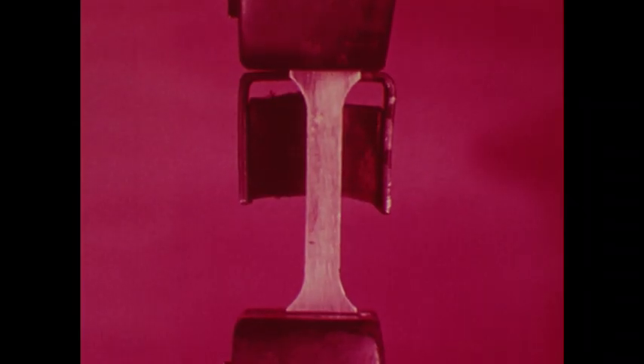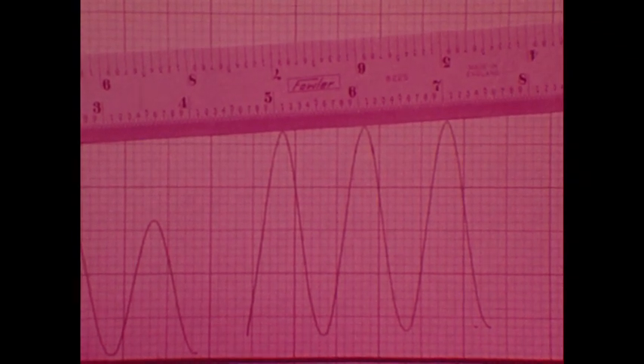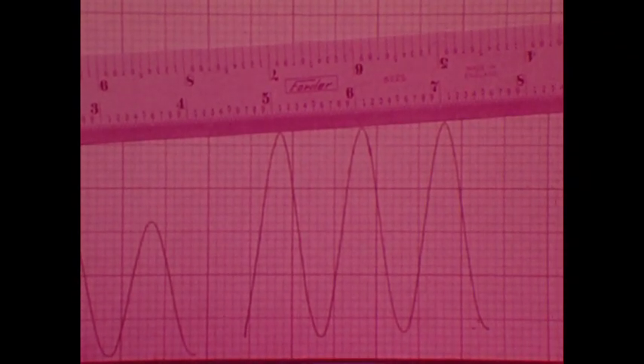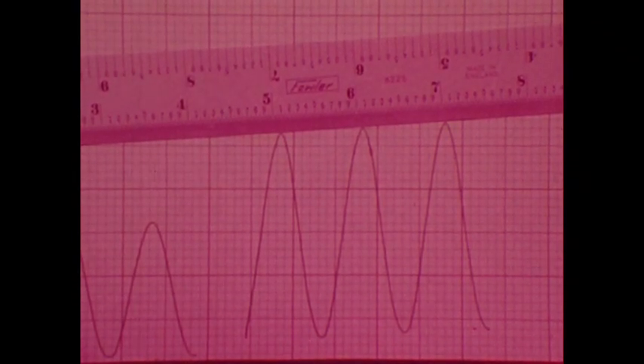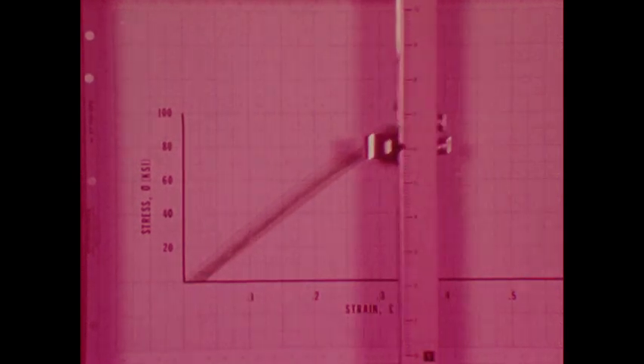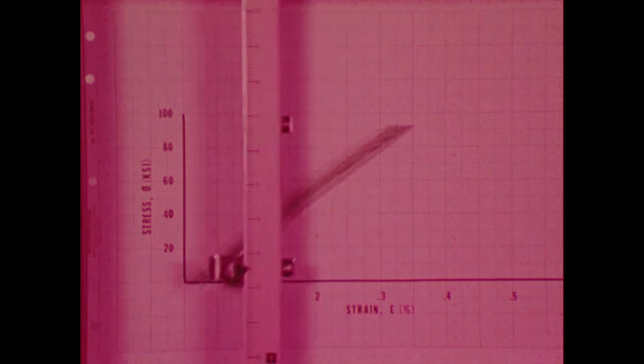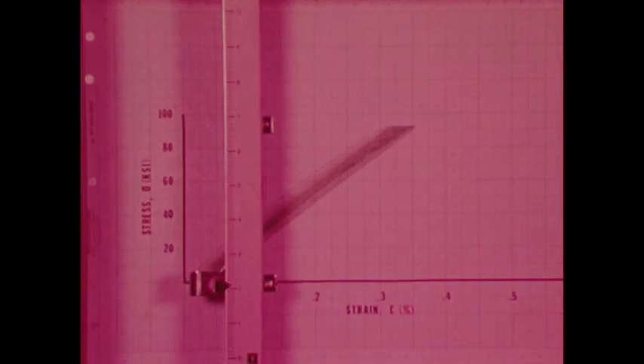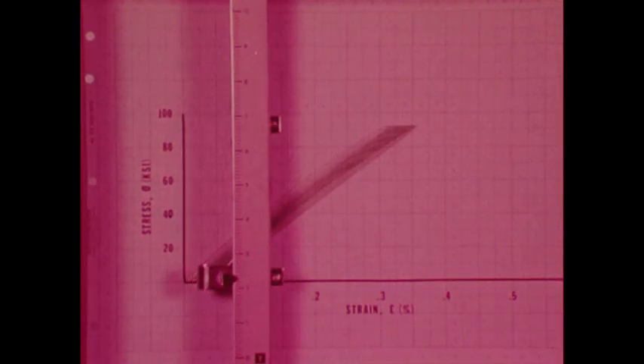But when large plastic deformations are present, as is the case for this aluminum specimen, the strain increases in each cycle. In such a case, the dynamic stress-strain diagrams move forward. Eventually, they become unstable and elongated. Within a few cycles, the specimen starts necking and finally fails. Such conditions usually lead to low cycle, that is, short life fatigue.